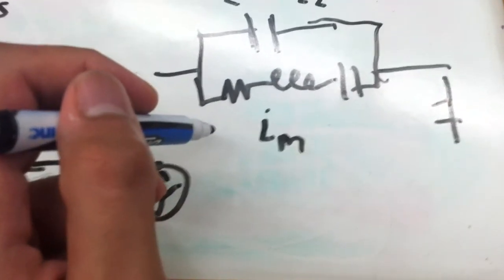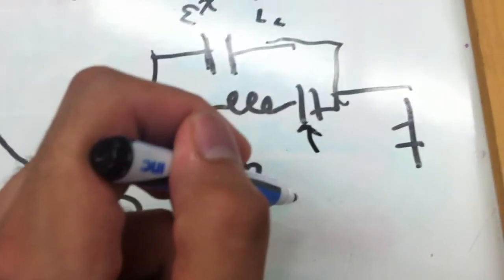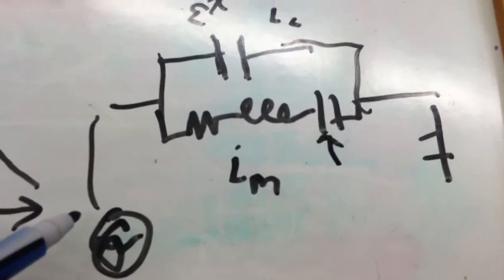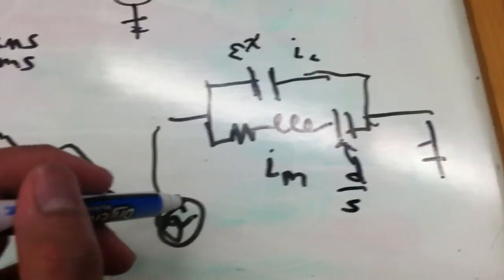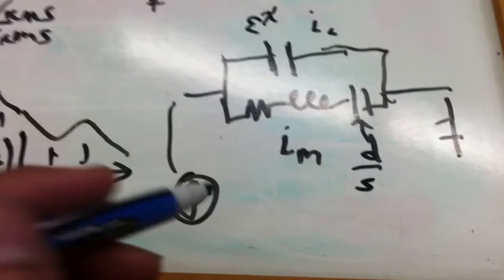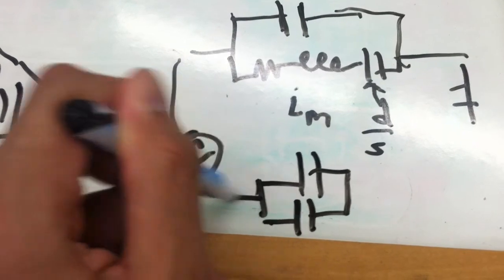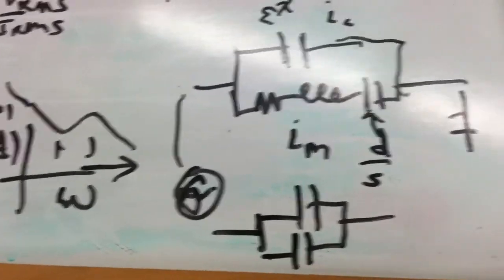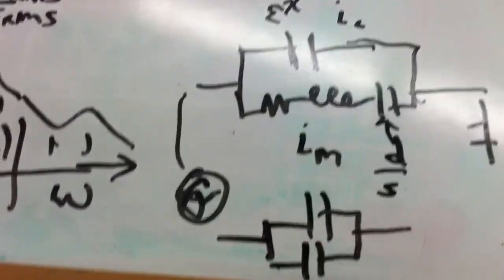And here in the bottom branch, we have an LCR resonance circuit. This capacitor here is representative of that energy which is introduced to the material when you apply an electric field. At off-resonance, K has to do with the piezoelectric d constant and the s coefficient. So when you apply an electric field at approximately DC conditions, 1 kilohertz is also approximately DC, you get these two capacitors only adding up together because they're in parallel, because this resonance circuit is not active. It's not really participating unless you're at the resonance frequency or in that region.